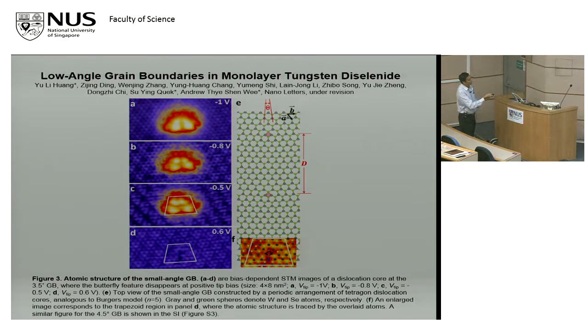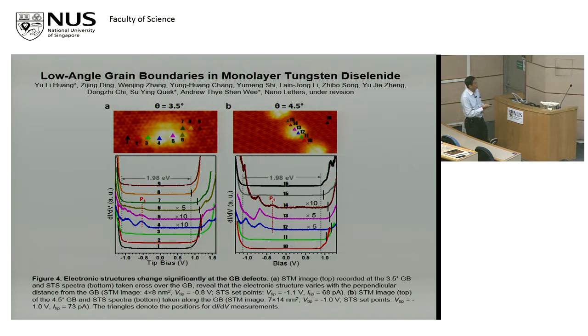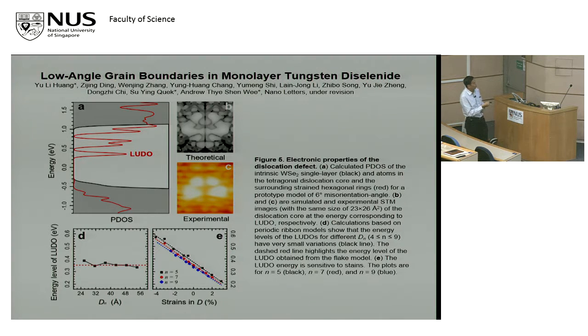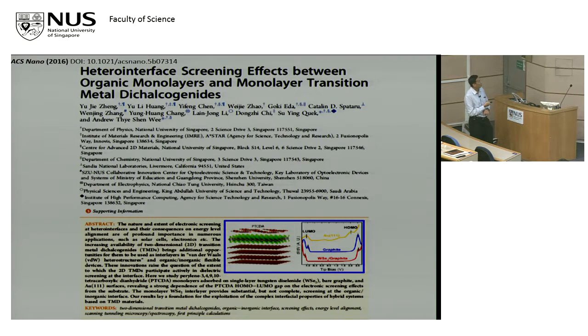So we worked out what we believe to be the structure at this location and measured the density of states, the electronic structure, at different positions around this location. And again, Suing's group, and Zhijing, did the DFT calculations, looked at electron states and matched the predicted gap states to the measured gap states. So that's the gist of this paper, which I won't go into too much detail.